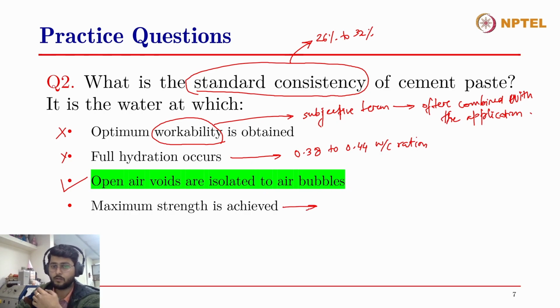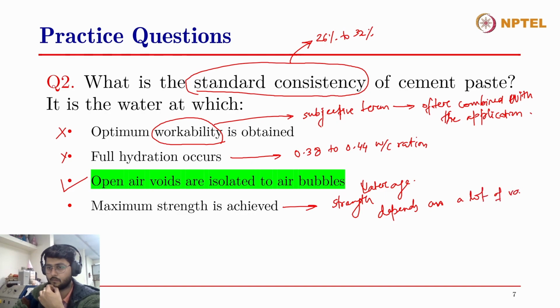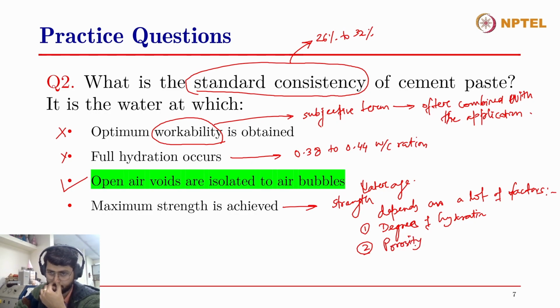Strength, and this is the ultimate or later age strength I'm talking about, depends on a lot of factors. One could be degree of hydration, and the major factor that governs strength is porosity, because if the voids are less inside the concrete, then the strength will be higher, and so on. So there are a lot of factors that govern the strength, and not just the standard consistency of cement paste will ensure that the maximum strength is achieved. So it is not the right answer.